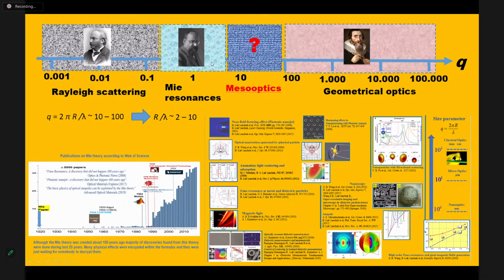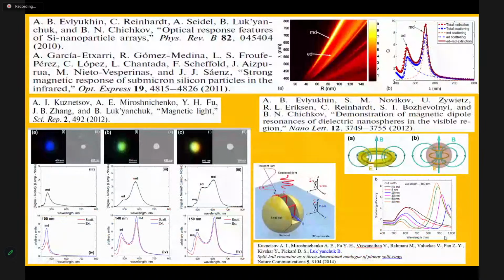But between the region of Mie resonances and geometrical optics exists some other area which is now called meso-optics, with size parameter of the order of 10. It corresponds to variation from 10 to 100, or ratio of radius to lambda from 2 to 10. In this area was found a lot of new physical effects, starting from photonic nanojet, magnetic light, film nanoscopy. I have no time to discuss all of these effects, so I will concentrate only on the ability to create huge magnetic fields during scattering.